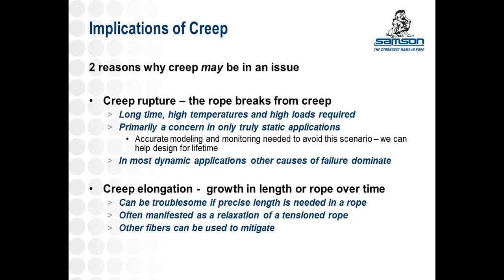This is, like I said, often manifested as a relaxation of a tensioned rope. And if this is the case, there's other fibers that can be used to mitigate this phenomenon. As I pointed out in the very beginning, creep rupture is something that happens in almost all materials. The difference between something like polyethylene, Dyneema, and some of the other high-performance fibers is while they have a creep rupture as well, before they break, they usually will have stretched much, much less. As I said, we generally consider the end of useful life to be about 10% strain due to creep on Dyneema. With an aramid or an LCP or another high-performance fiber, you might only see 0.5% strain before that rupture takes place, but the phenomenon still does occur.